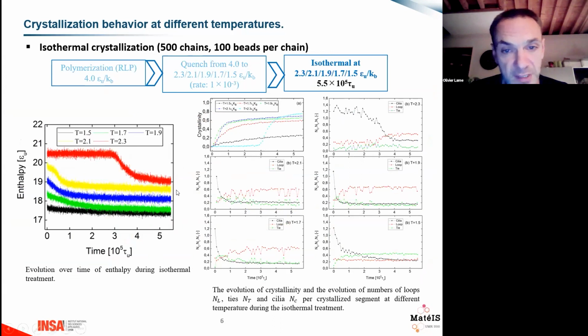Okay, we have also measured different properties of the amorphous phase on this system: the number of cilia, the number of loops, the number of tie molecules. I won't describe it in detail here; I will do it just after. But we have checked that these molecules behave realistically, because we don't have any clear information from reality, since it's just a point. We have just looked at whether these evolutions are realistic. In particular, the number of cilia decreases with the increase of crystallinity, which is quite logical because the chain goes more and more into the crystallite.